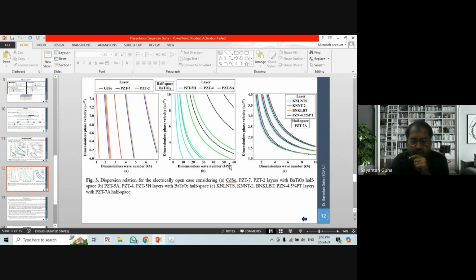But when we go for higher wave numbers, we see that the phase velocity is least for PZT5H, followed by PZT4, and then by PZT5A. So if I compare the contents of figures A and B, we can see that overall, for all wave numbers, the phase velocity is least when the layer is composed of CdSe and the half space is composed of BaTiO3 for the electrically open case, which implies that the CdSe BaTiO3 combination for the electrically open case is going to be more suitable for a SAW device.